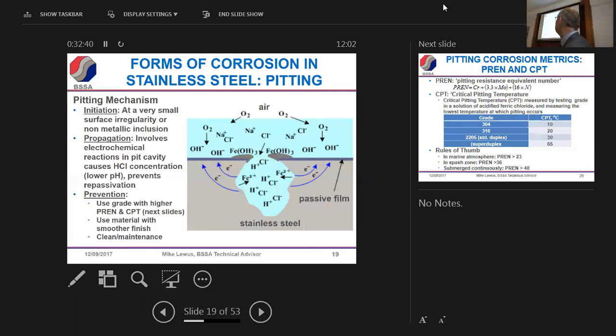The pitting mechanism, without going into the science of what's happening, the breakdown of the passive layer is occurring, and the electrochemical reactions that occur in a typical pit do actually produce hydrochloric acid. And it's also what's termed an autocatalytic reaction. It accelerates as the process is going on because the concentration of hydrochloric acid is increasing. So we've got an anode here, we've always got a cathode where some sort of oxidation of the